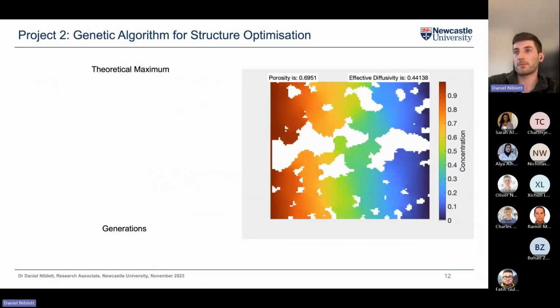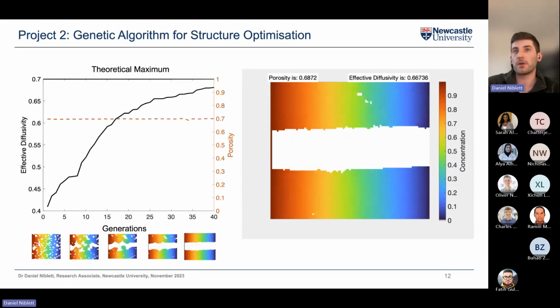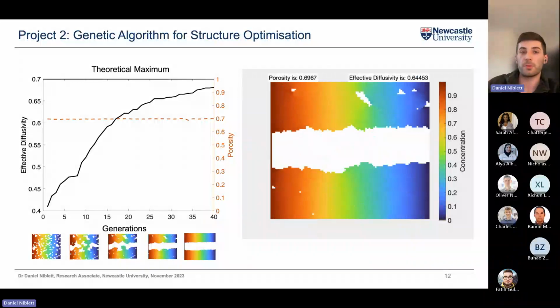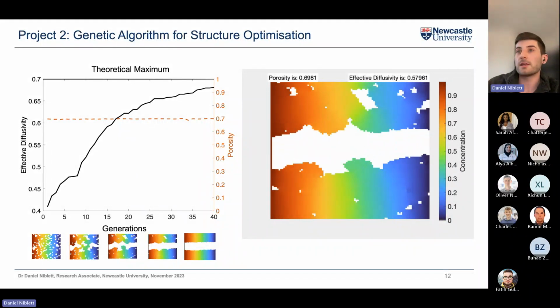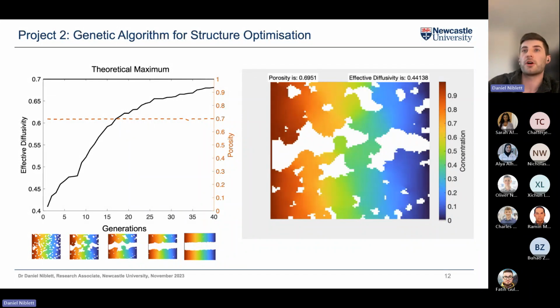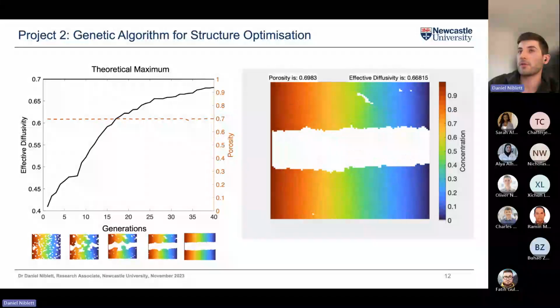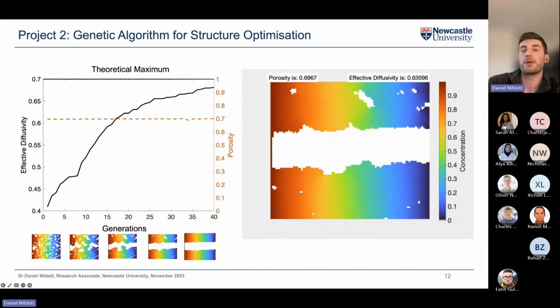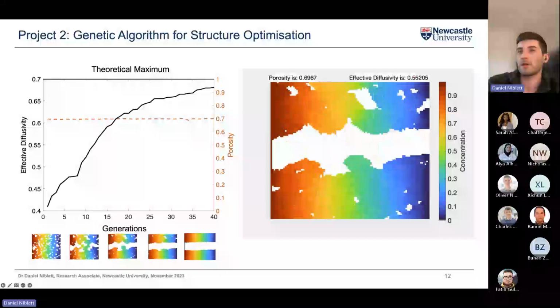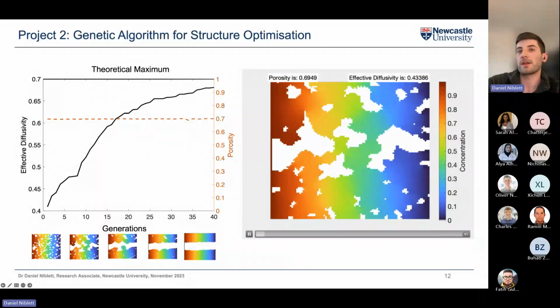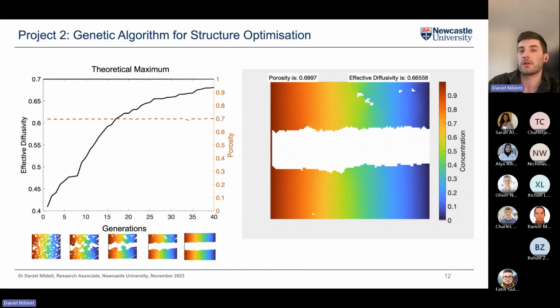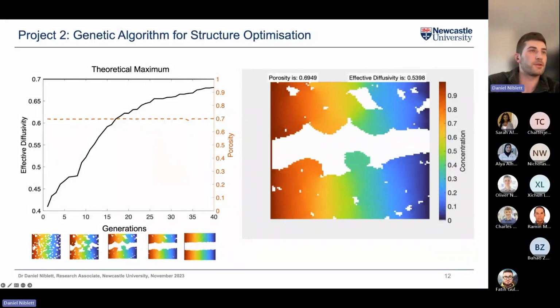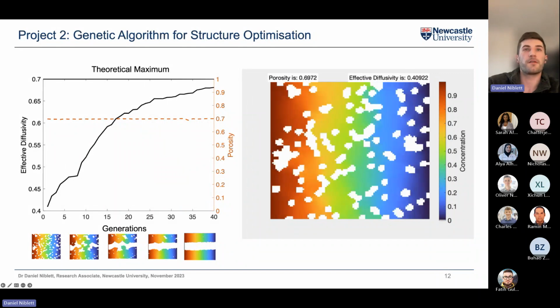And we can see this algorithm actually working here. So I've just got it to loop the video here. So without any human input from myself, this structure optimizes itself to close to the theoretical maximum, whilst also constraining the porosity. So the porosity stays constant at 70% here. So that's a constraint in the system to try not to remove any solid particles. And as you can see, over 40 generations, we move from 0.4 to around 0.65 effective diffusivity.